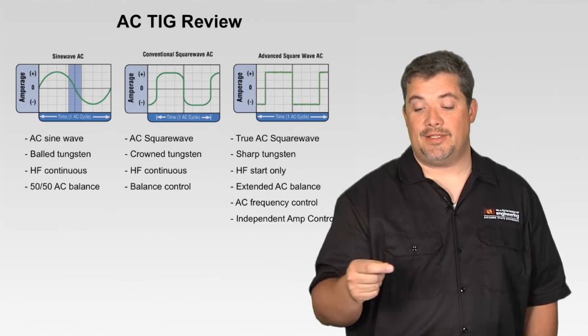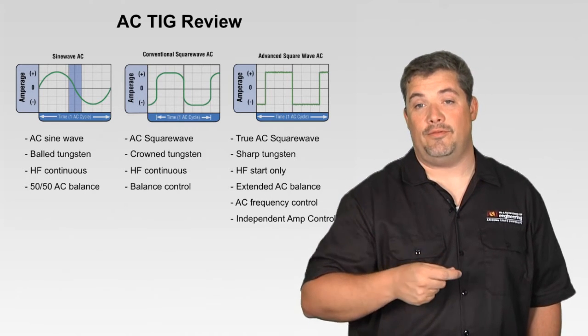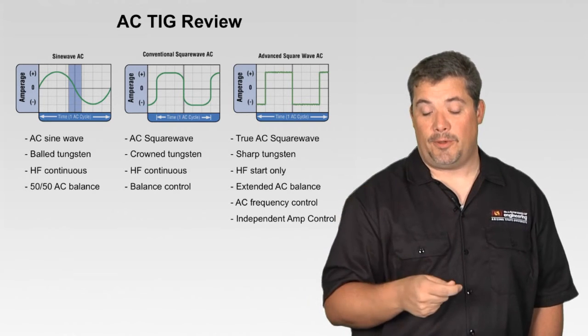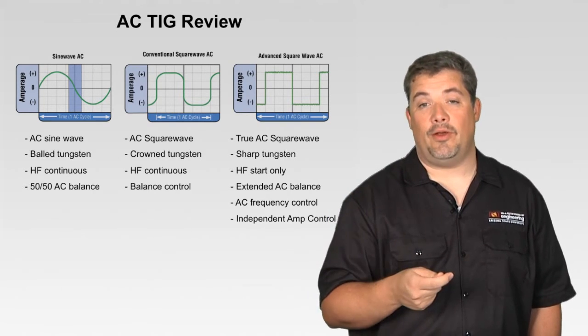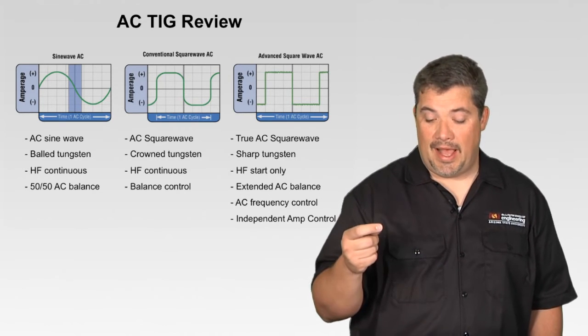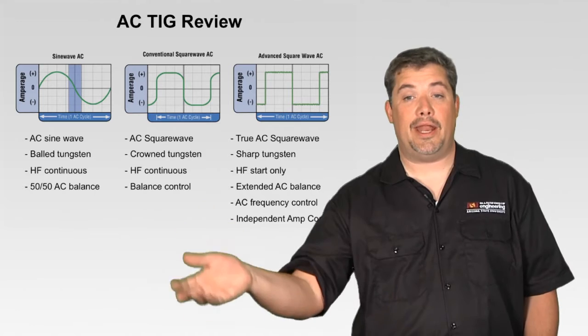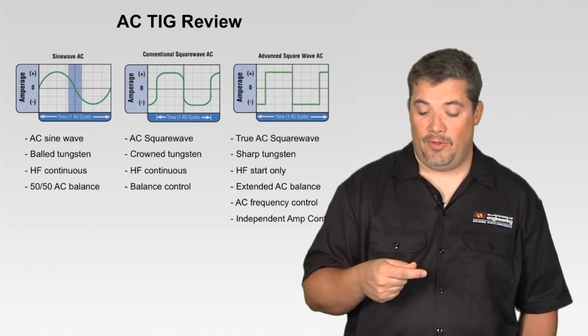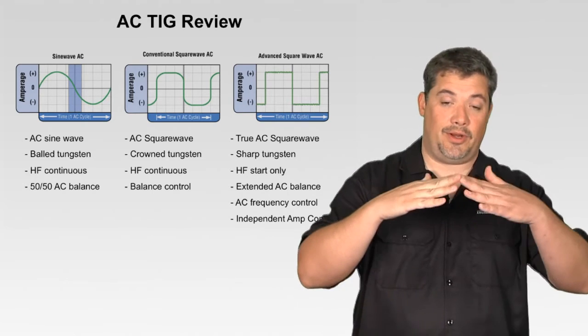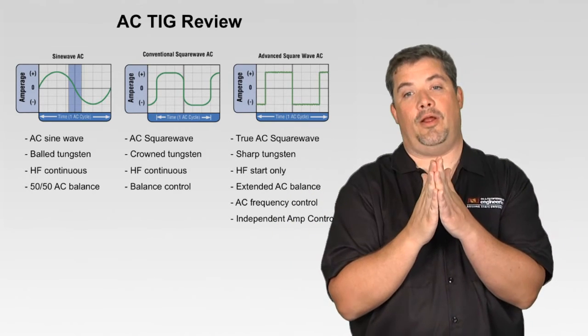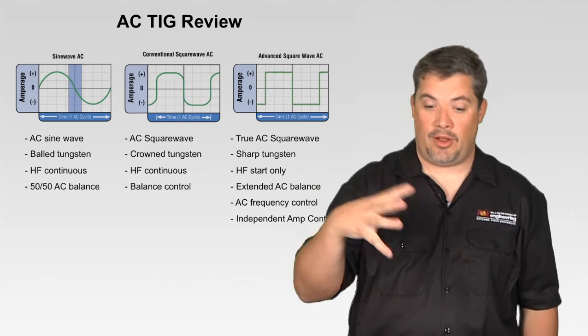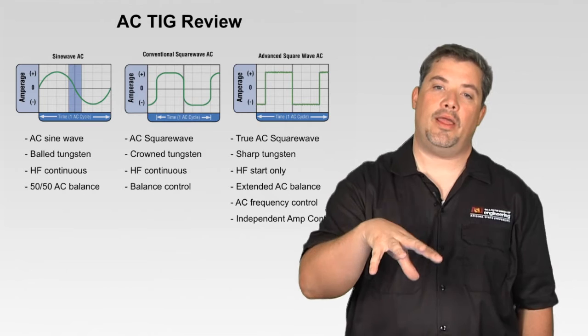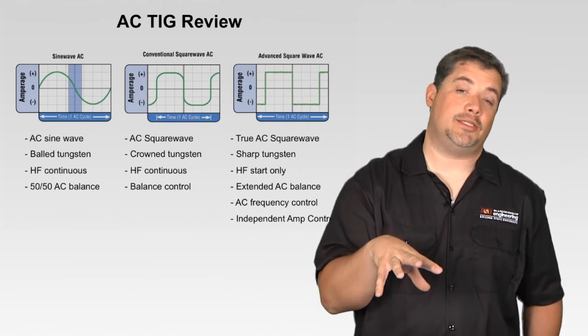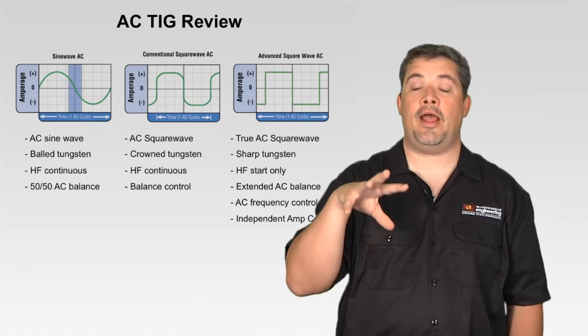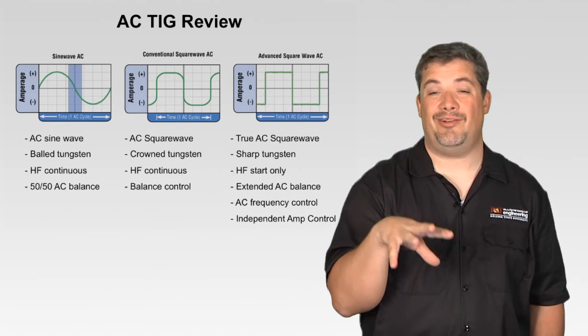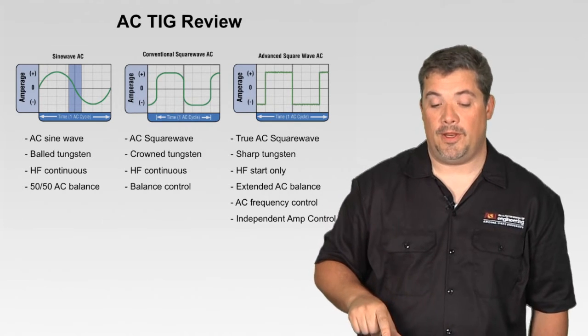Then came along these advanced square wave ACs that use a true AC square wave shape, but also the options to do others. I use a sharp tungsten rather than a ball. I use high frequency only to start the arc rather than have it on all the time. I have the extended AC balance control from 30 to 99%. I have that AC frequency control, instead of that limited 60 hertz, I can go down to 20 hertz and widen my arc, go up to 400 hertz and focus my arc. I have independent amperage control to control how much energy is going into that part to help me make that weld as efficiently as possible, whether it's in shape, whether it's helping to do certain alloy things, whether it's controlling how much heat is in there for heat treatability. So much more capability than ever before.